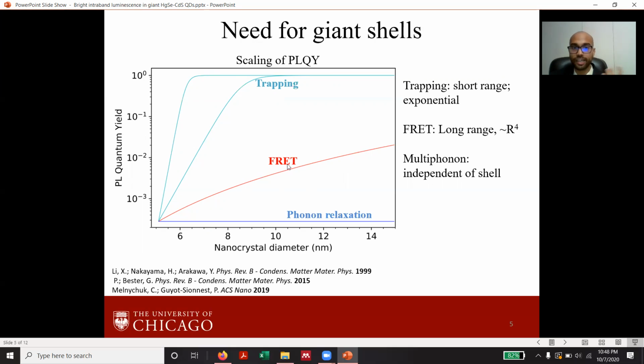If FRET is the dominant mechanism, then the lifetime would follow this trend in the red curve, which is the fourth power of radius scaling. And if it is dominated by multiphonon relaxation, the lifetime would be independent of the thickness of the shell. So from this plot, we can see that by growing a giant type 1 shell on our core, we can find what is the dominant non-radiative mechanism at play in the nanocrystals.